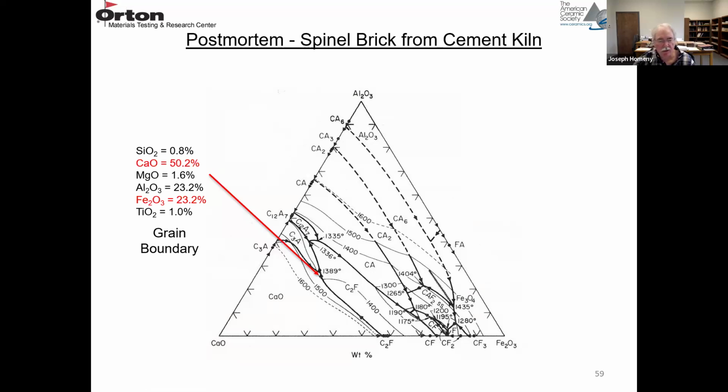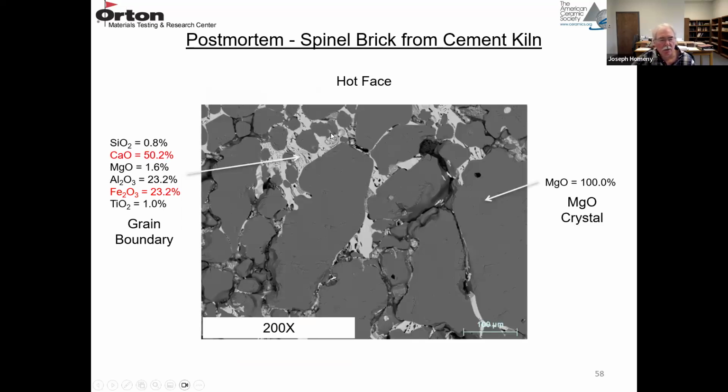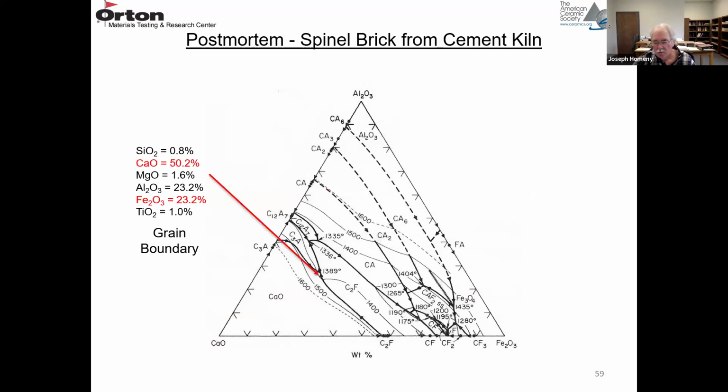That's lower than about 1500 degrees C, where your furnace is operating. So this should be a liquid phase at temperature. Keep in mind that all these polished sections are made after the refractory cools down at room temperature. So this looks like it was a liquid phase. And you can see it's starting to dissolve the smaller MgO crystals. So that's what I have to finish up a glass tank and at least 3 examples on cement furnaces.